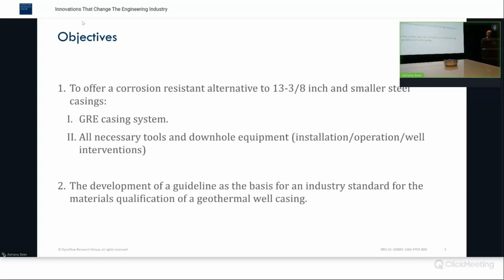Corrosion of the conventional steel casing is a serious problem. A recent investigation by SODM showed that more than 50% of the current geothermal wells in the Netherlands showed wall thickness reduction of 25 to 85%. That is mainly because the geothermal wells in the Netherlands have a high salinity level.